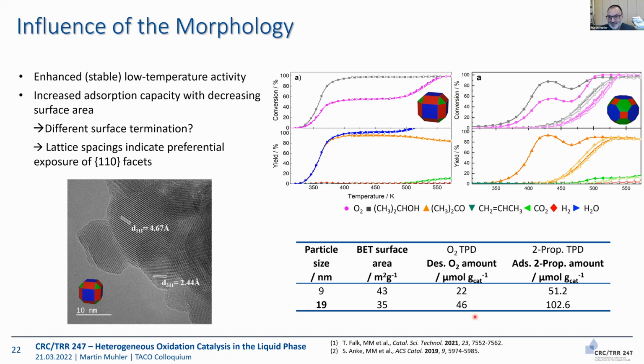And the very nice result was, this is what you have seen before, the 9 nanometer particles, and now having the huge ones, where we claim that now we have much more of these 110 facets. Here we see that the low temperature channel is stable. It's actually stable for days. You can go to this temperature and keep it running, full conversion to acetone. That means these huge particles don't deactivate anymore.